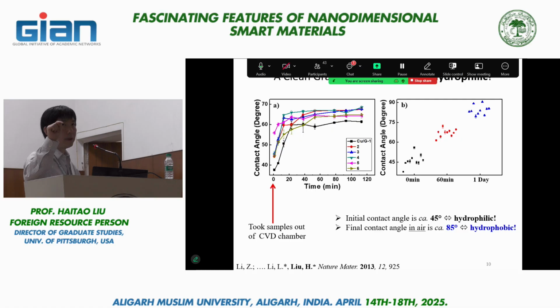about 2 hours. Now on the right-hand side, I show a similar kind of data collected from about 10 different samples. Same kind of idea, except I only show 3 different time steps: at 0 minutes, at 1 hour, and at 1 day. And what you see is, after 1 day of air exposure, the water contact angle measured on graphene actually comes to the literature data around 85 to 90 degrees.